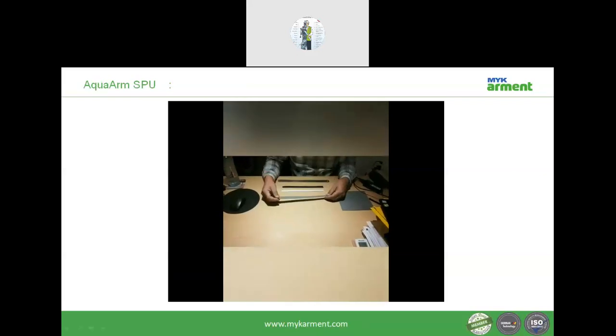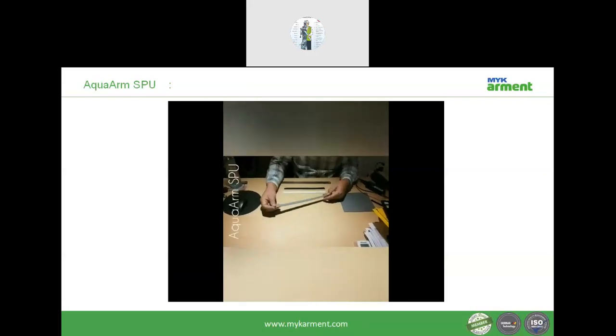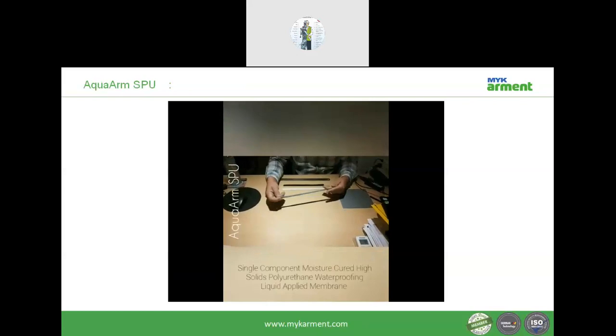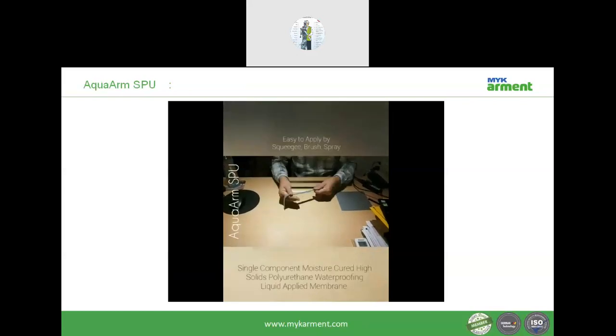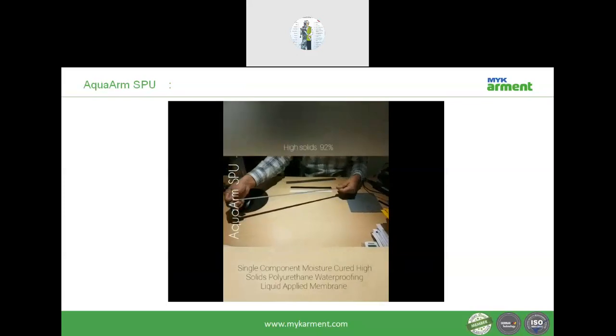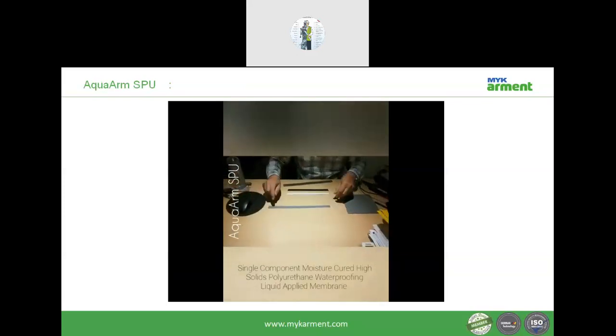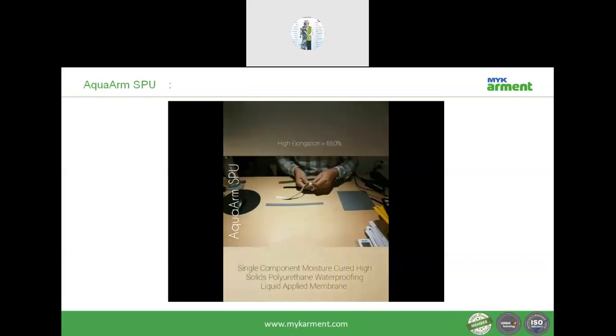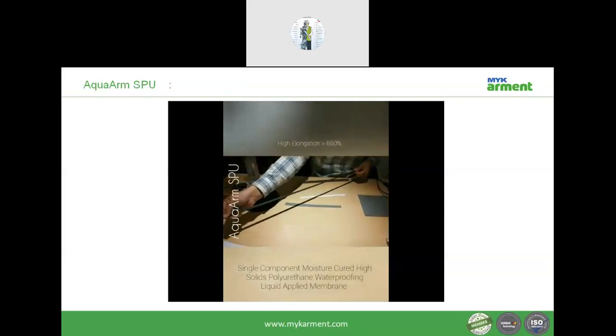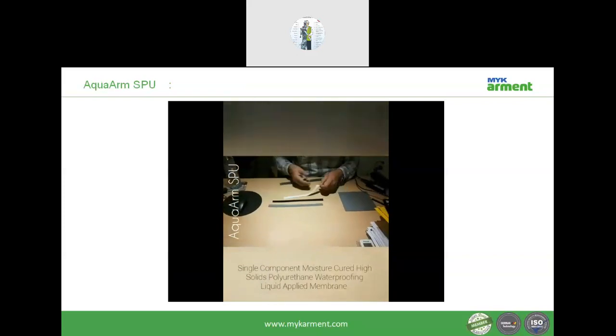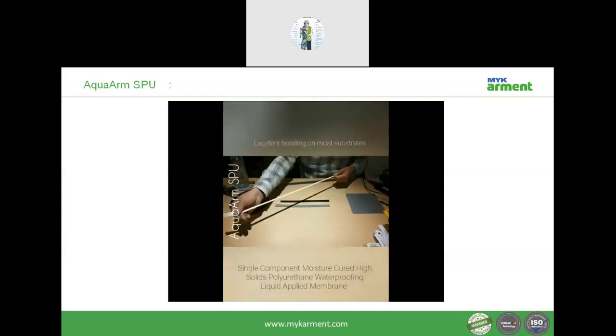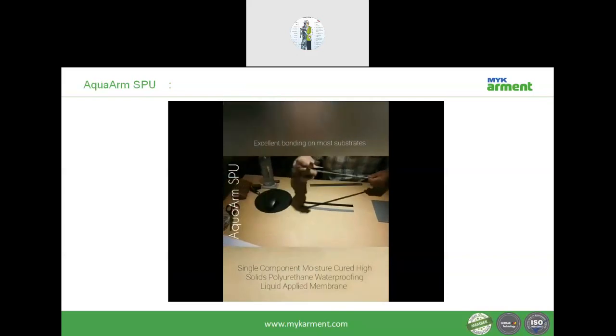And this is about our solvent based polyurethane based system, which has a high solid content, and you can see how flexible the material is. This is the flexibility of the material, which has high crack bridging properties of more than 2 mm, and it comes in the range of A5 of EN 1062. You can see how flexible the material is. It has high crack bridging abilities, and it has an excellent bond to the substrate.